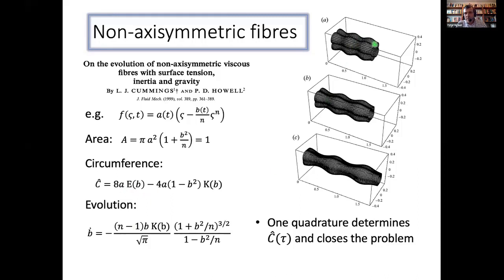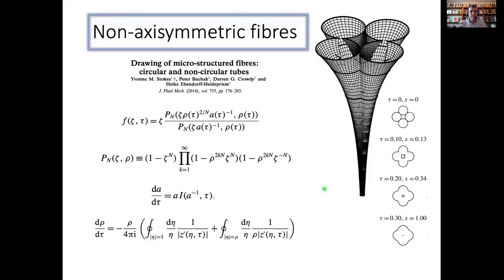So here we started with a sort of four lobed shape. And we gave it some sort of waves in the axial direction as well to see what would happen. And you stretch it out. And what you see is it evolves to this shape here. And so really the evolution of the cross section and the stretching in the axial direction are coupled to each other. And in particular, you could see that if I look at one of the thin bits, it's become almost circular. Whereas if I look at one of the fat bits, it's still quite bulgy. And that's a manifestation of what I said before about this reduced time, that the rate at which the cross section evolves depends on how big the cross section is.